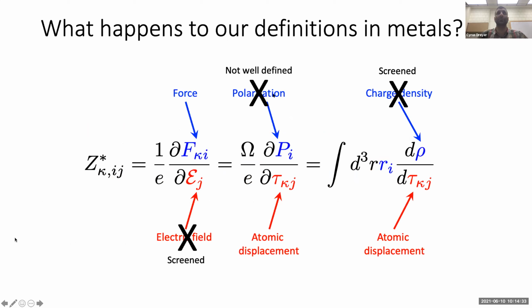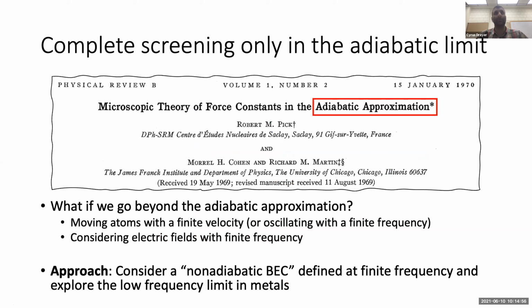And then, as we know from the work of David and Raffaella, the polarization is not well-defined in a metallic system. And so at first sight, the Born effective charges may be expected to either vanish or not be well-defined, and in any case, not be very useful for metallic systems. Now, of course, what many in the audience also probably already know is that those arguments are pretty naive, and they rest on basically the idea that atomic displacements or electric fields are applied in a very slow manner, and in that case, we can do our calculations or think about our materials in terms of the adiabatic approximation. The adiabatic approximation just says that, for example, atomic motion is so slow that electrons are always in their instantaneous ground states and therefore can move around and screen any fields or any electrostatic perturbations.